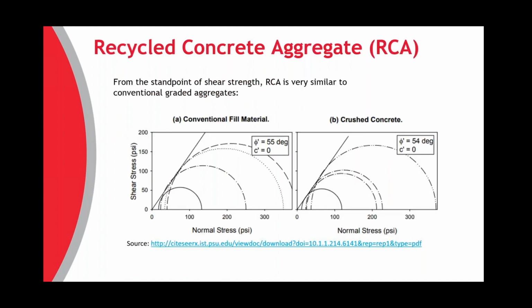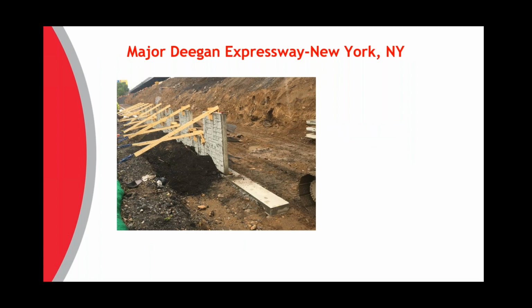All right, so recycled concrete aggregate. Shear strength is pretty much the same or very similar to what a conventional backfill material would be. This is a crushed aggregate at about 55 degrees, the crushed concrete about 54, so essentially the same strength. And to give you an example, this is a project that Tensar was involved in in New York, the Major Deegan Expressway. About 200,000 square feet of wall face area. It required 100,000 cubic yards of reinforced backfill.